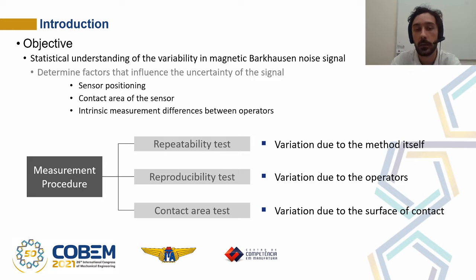The study was conducted using repeatability tests, which aim to analyze the variation of the signal as a function of the method itself, reproducibility tests, which aim to identify variations caused by the operators, and the test of the surface contact area of the sensor with the sample, in order to investigate the variation as a function of the contact area.